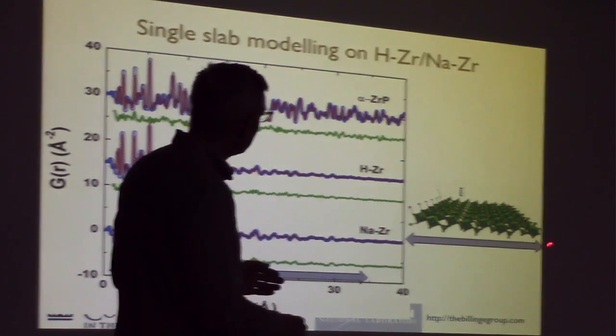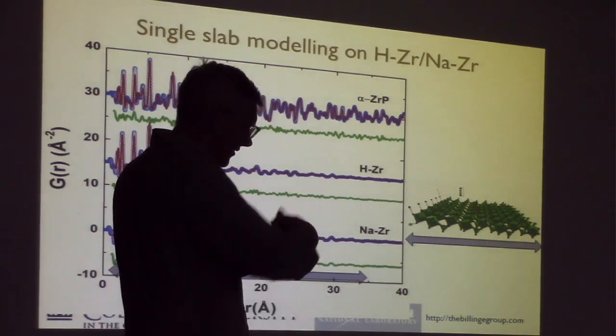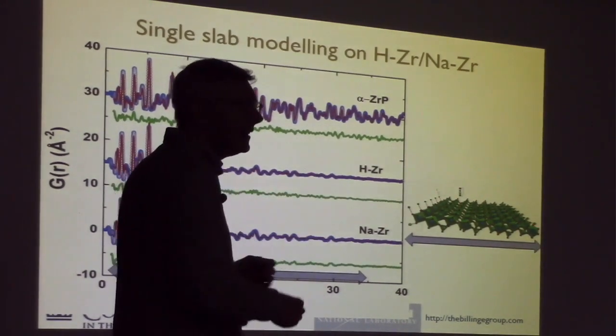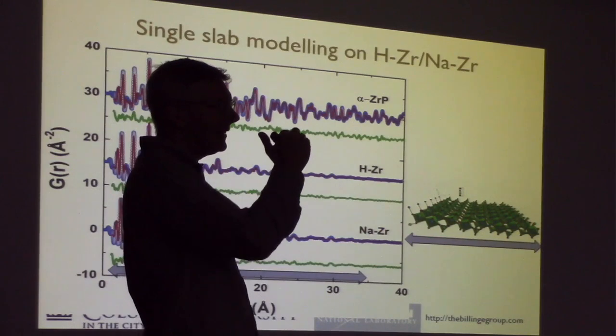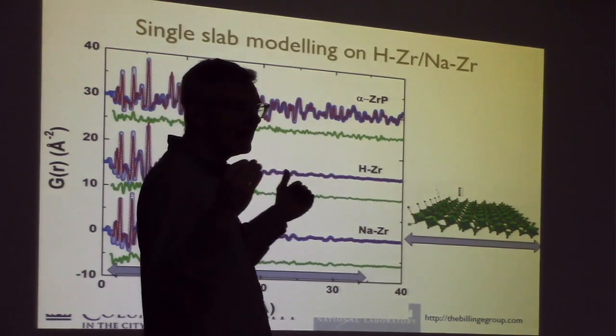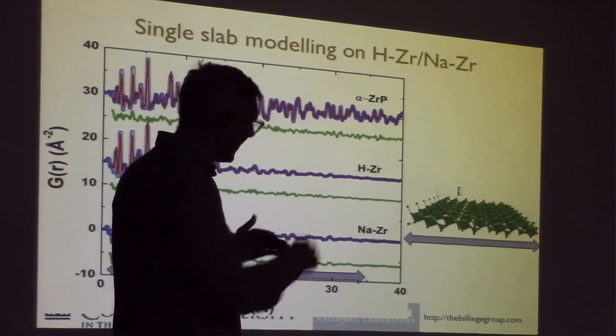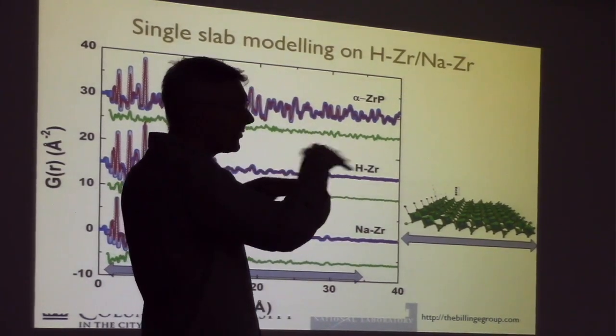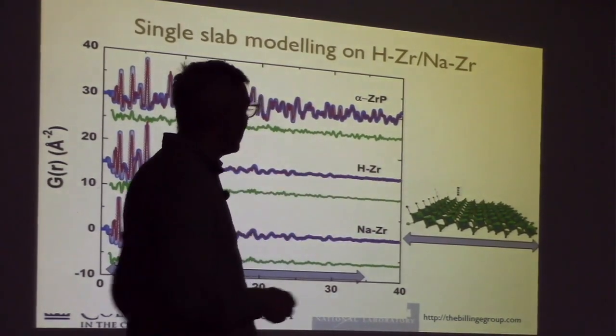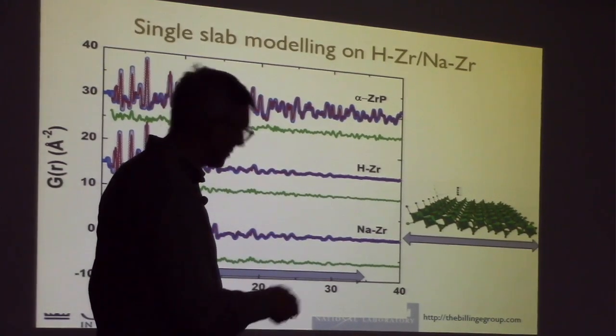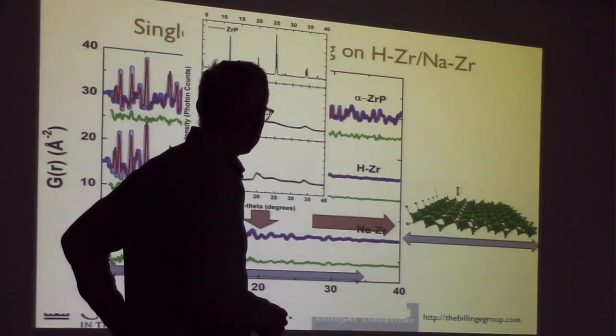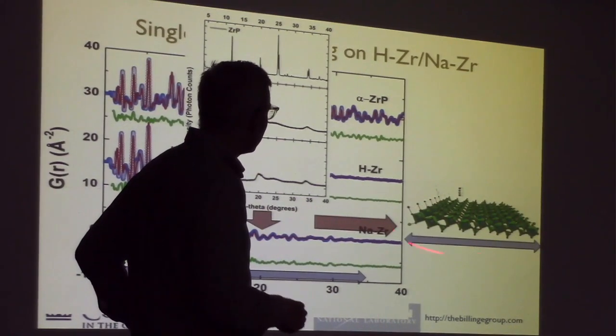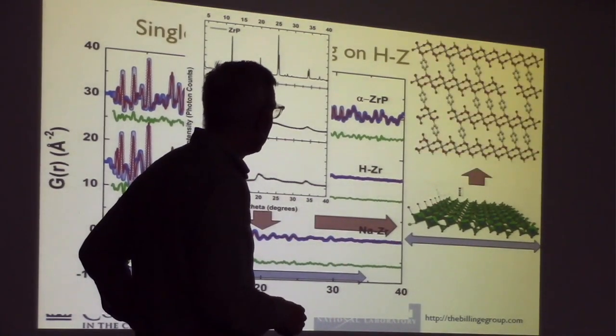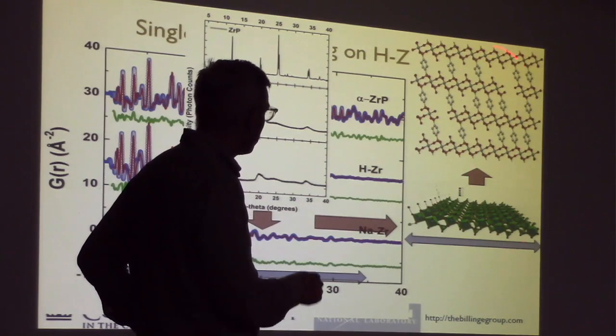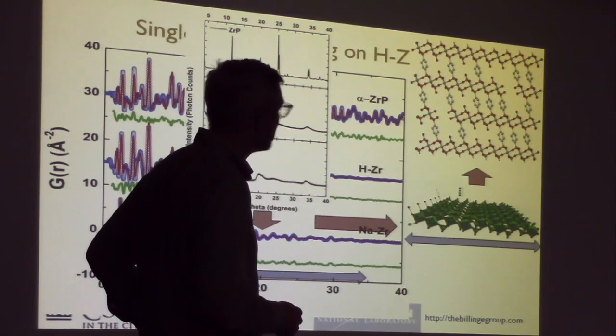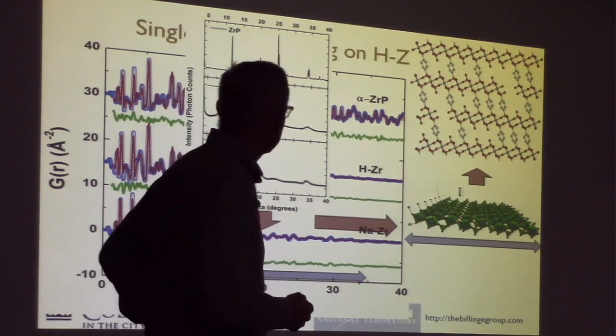So one possibility is that the material is made up of stacked sheets that are this size. Another possibility is that these sheets are buckled and bent. And when they buckle and bend, we start to lose correlations, lose coherence. And so this is the size of the range of structural coherence. So we can get this nice layer structure and the coherence length. Once we have that, we can build up more three-dimensional models like this, and we can start getting a much better understanding of what the real structure of these materials is.